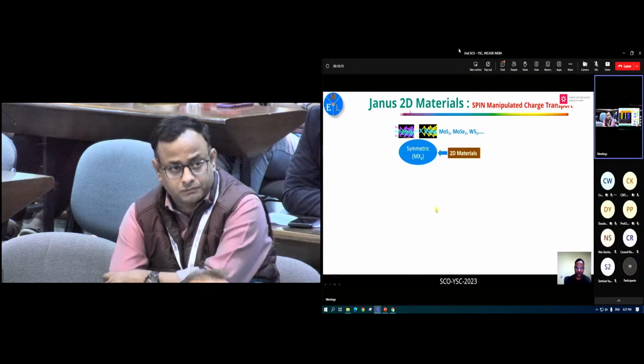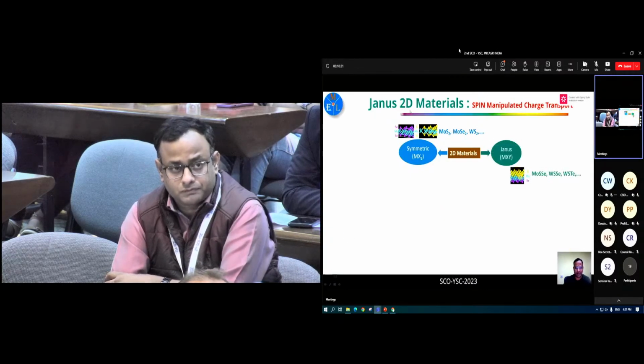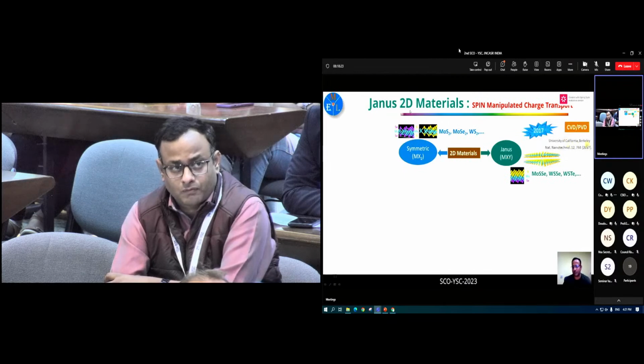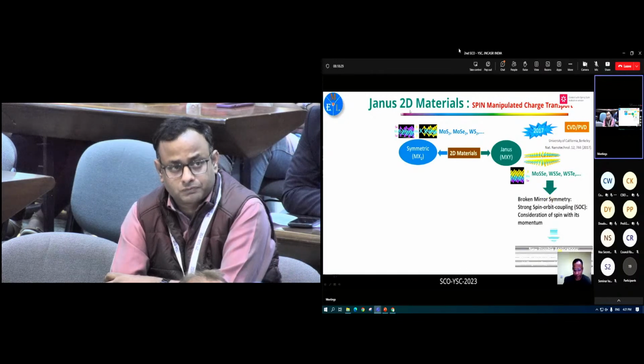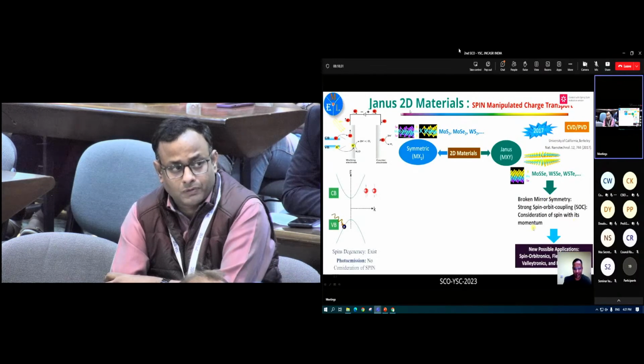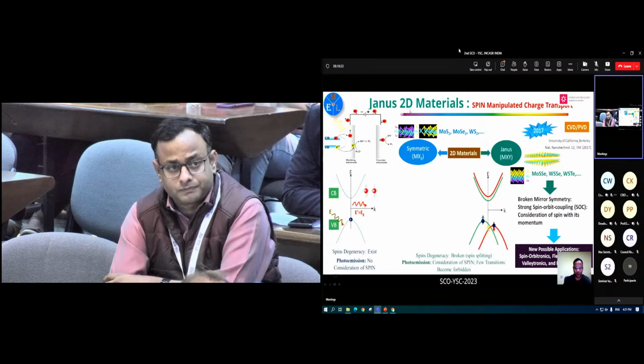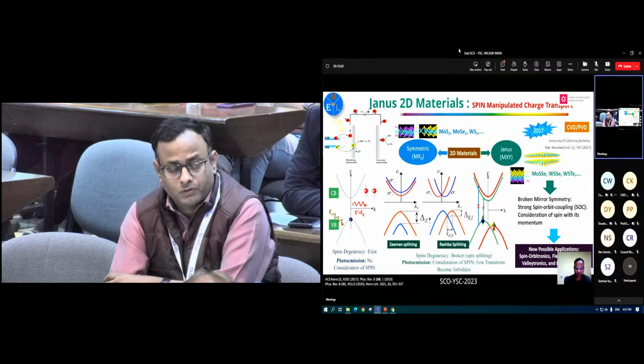Then we try to understand the asymmetric 2D material, which was first invented in 2017 by the University of California. Because now the symmetry is broken, they have a strong spin orbit coupling. Once they have spin orbit coupling, their spin degeneracy is broken, so you have different states for up spin and down spin. This is basically called the Rashba splitting. So your transition becomes forbidden, and under the magnetic field you can manipulate the spin now.